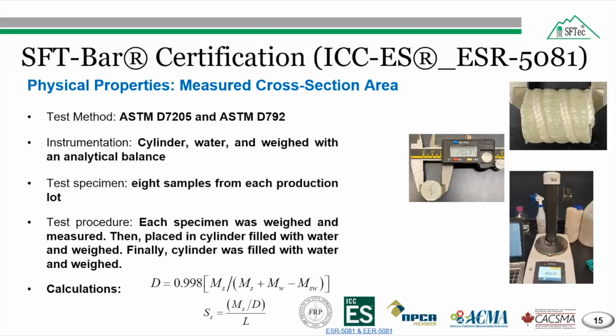So 8 samples from each production lot were tested. The total number of lots was 3, so the total number of samples was around 24. Each fiber reinforced polymer specimen was weighed with an analytical balance to a 1 milligram precision, and its length carefully measured with a measuring scale. Then the specimen was placed in a graduated cylinder filled with water and weighed. Finally, the cylinder was filled with water and weighed.